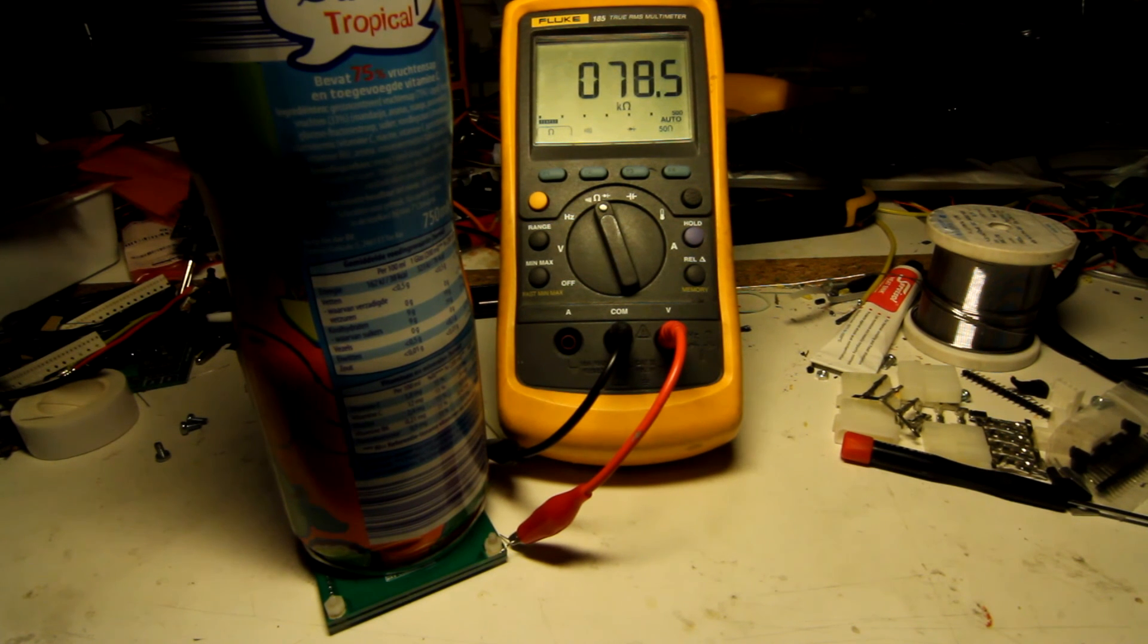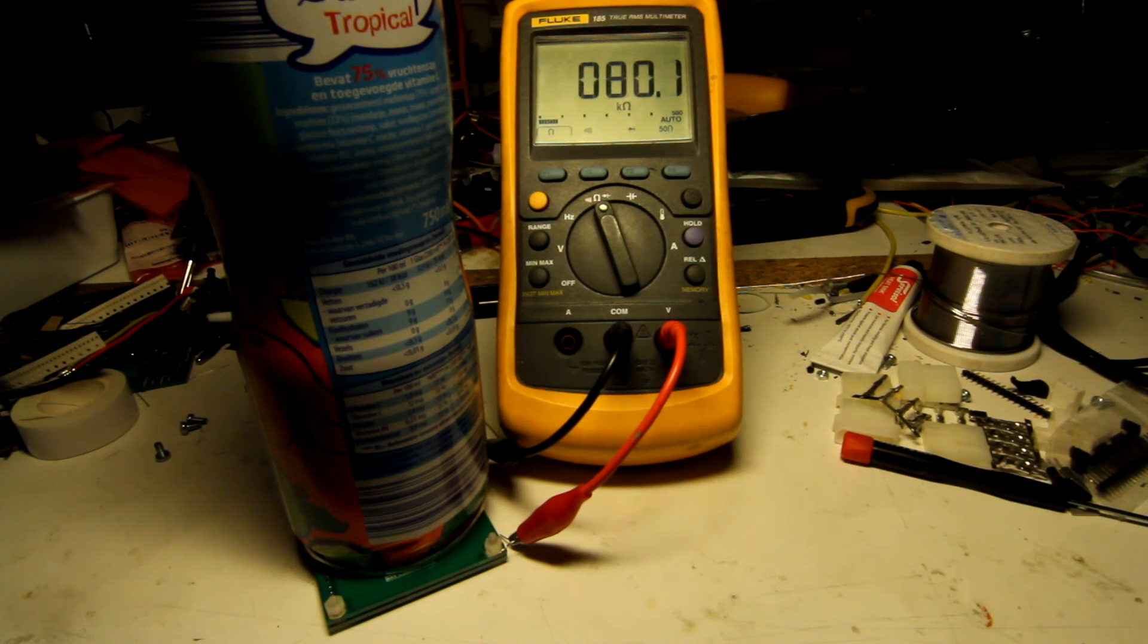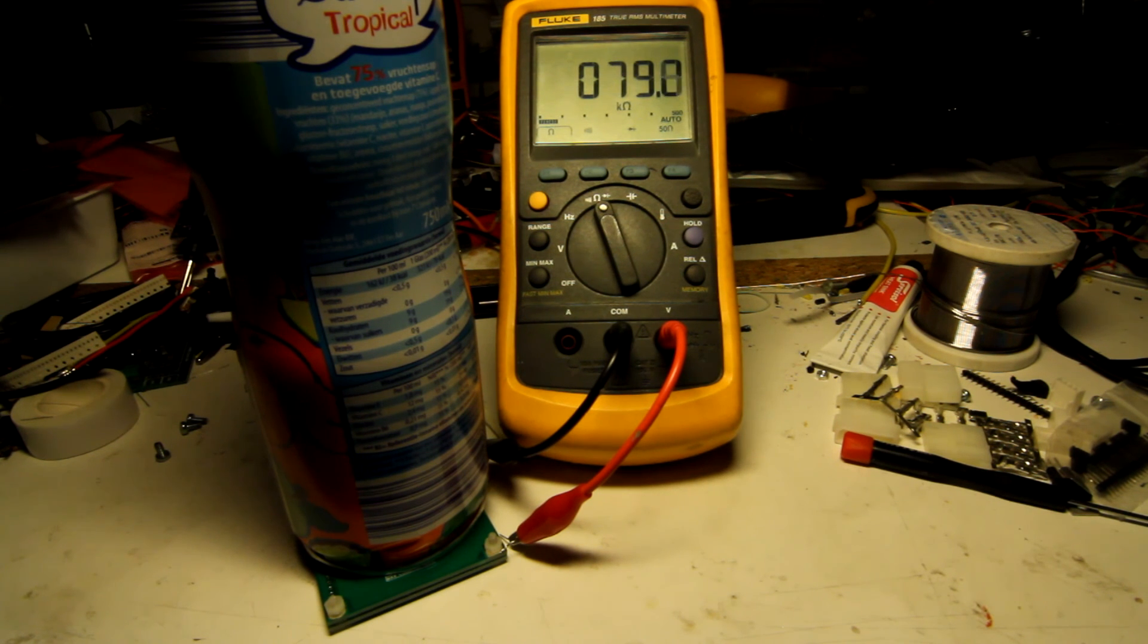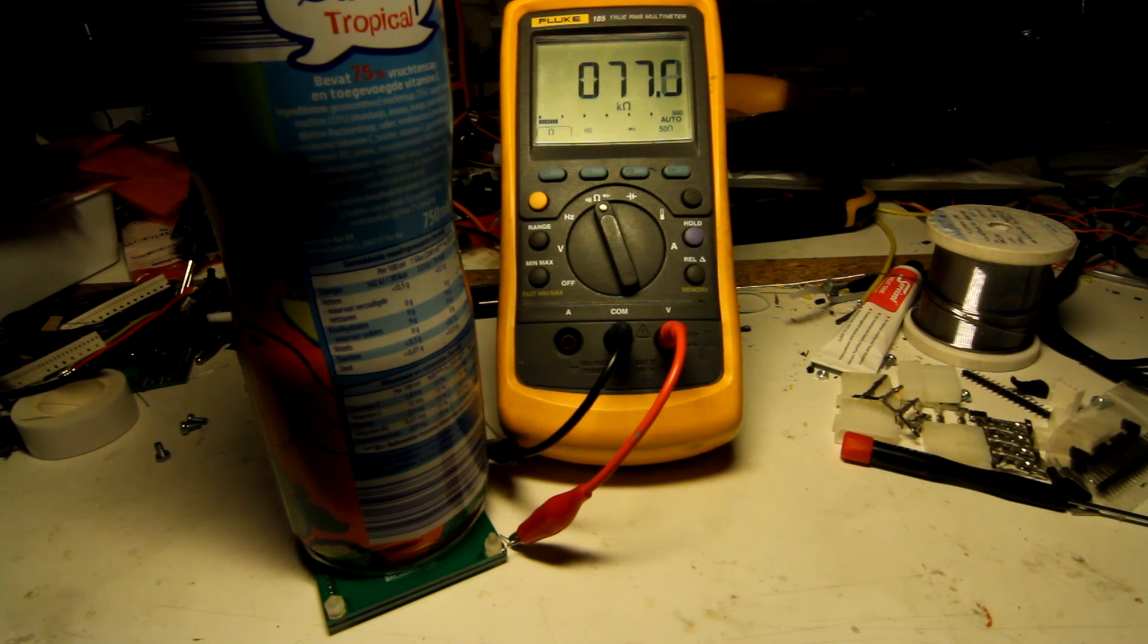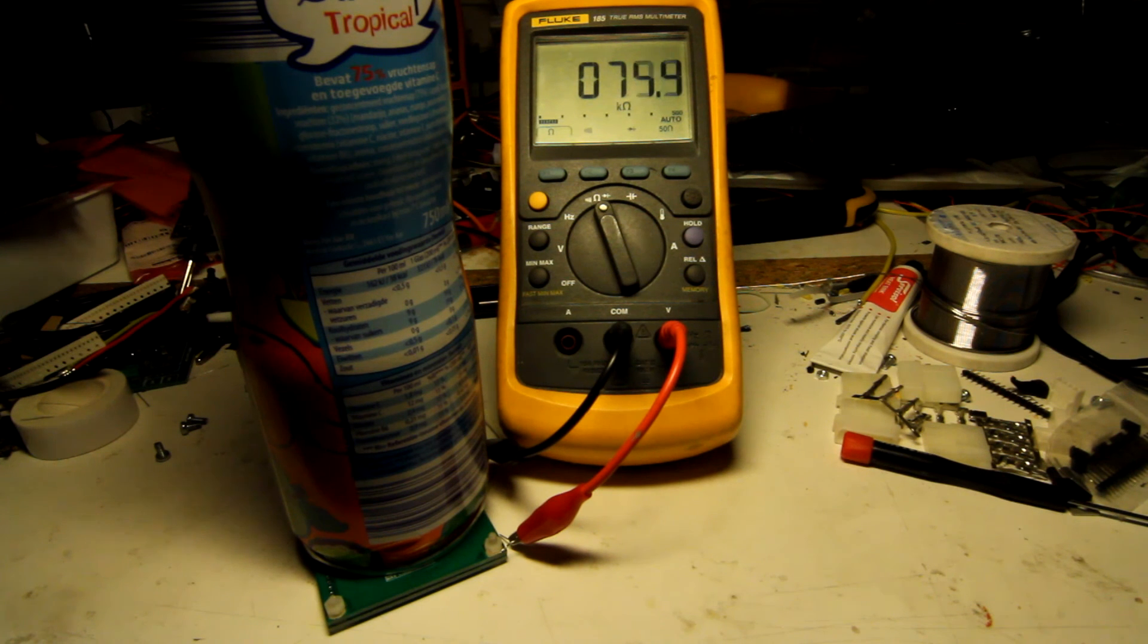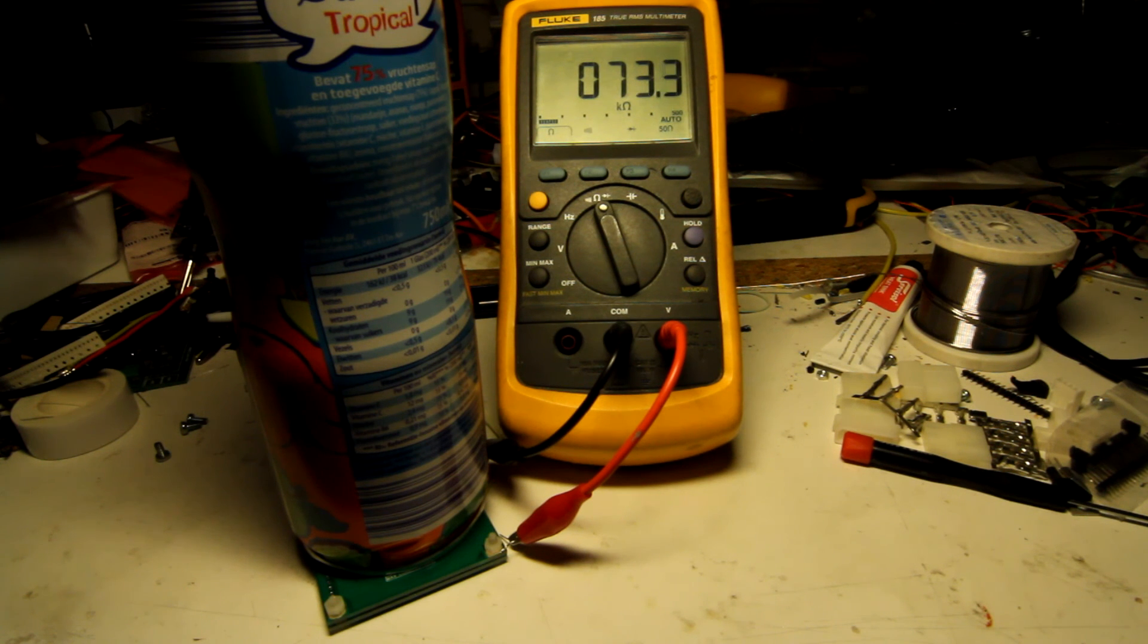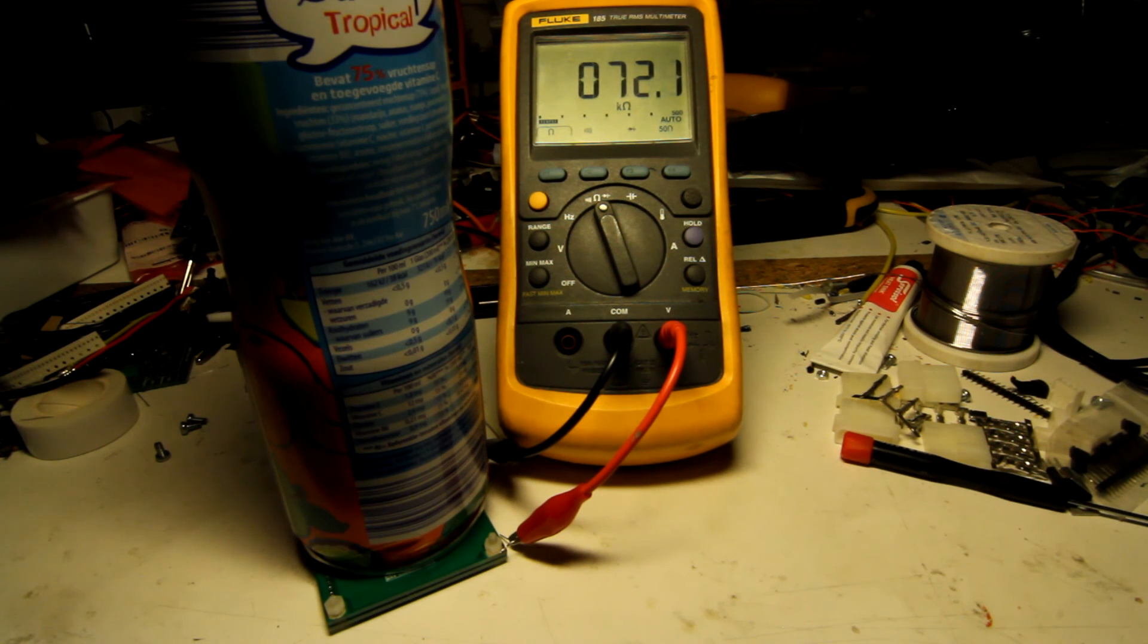Now, of course, another issue with quantum tunneling composites - it's really nice that they respond so strongly to compression. But one of the downsides is that the surfaces between which this QTC is sandwiched need to be really coplanar - perfectly parallel. Because if one of the corners of this QTC is just slightly more compressed than the rest, that corner is going to conduct so much more that it drowns out the resistance signature at the rest of the material. So it's just really hard to get such a QTC to respond linearly to a certain load.